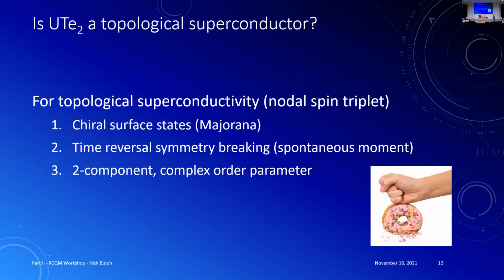So I will say it explicitly, this is not a ferromagnet, and I had to skip a bunch of slides just in the interest of time, but we can at least make a checklist, say what kind of properties we would expect of a topological superconductor. I argue you would want to show that you've got some kind of chiral surface states, break time reversal symmetry, and in order for this to happen, you need to have a two-component order parameter.